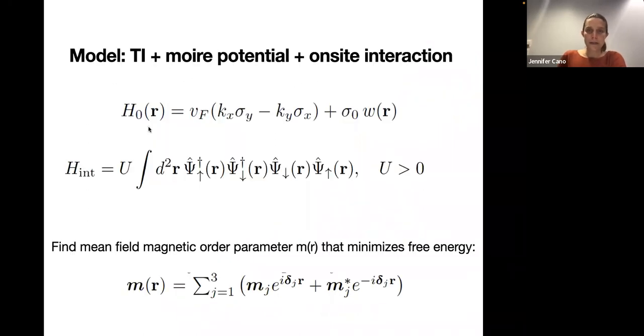Okay, so to be concrete, this is what we computed. We have our Dirac cone, we have our superlattice potential, and we have the Coulomb interaction, which we just treat as an on-site Hubbard type interaction. We take it to be repulsive from electron-electron repulsion. And then we look for a magnetic order parameter that's going to minimize the total energy of the system. And that magnetic order parameter is subject to the constraint that spatially it's modulated. And those spatial modulations are determined by the distance between these Van Hove singularities.